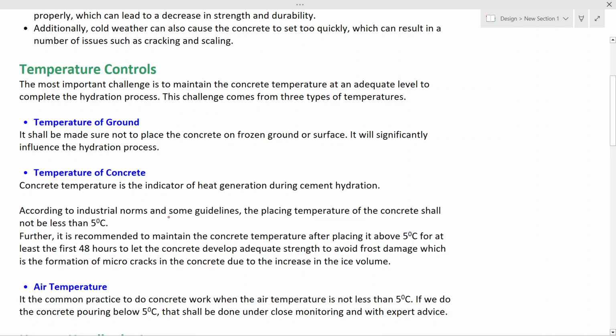It should be above 5 degrees Celsius for at least the first 48 hours to let the concrete develop adequate strength to avoid frost damage, which is the formation of micro cracks in the concrete due to the increase in the ice volume. Therefore, we have to maintain the concrete temperature at least above 5 Celsius for the initial 48 hours.